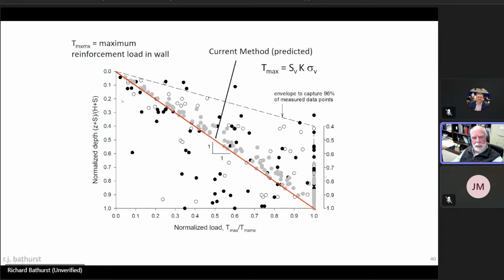The light gray symbols that you see here are the predicted values, assuming the current limit equilibrium method of calculating loads in reinforcement layers. And you can see they fall more or less linearly with depth. The measured results, which are the open circles and the filled circles, are actual data. And if you want to capture that data, then you're better off with a bilinear distribution, not this linear distribution.